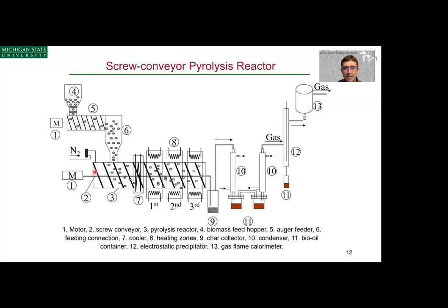What we have at Michigan State is something in between fast and slow pyrolysis. Our residence time is on the order of 20 to 30 seconds. This is a screw conveyor pyrolysis reactor, and up here at 4 is our feed hopper. The biomass goes into the feed hopper and then down into the reactor barrel. We have 3 heating zones, and we can control temperatures up to about 550 degrees Celsius. What comes out of the reactor is biochar and pyrolysis vapor.